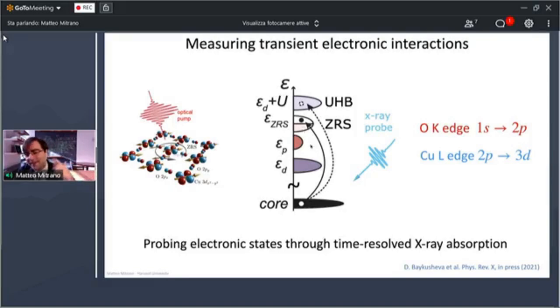The key thing that you have to keep in mind for the interpretation of what comes now is that by absorbing X-rays from core states, we can actually induce transitions into unoccupied states and therefore measure the unoccupied density of states of this material. We can send electrons into the Zhang-Rice singlet, into an unoccupied portion of the Zhang-Rice singlet, or into the upper Hubbard band. And we performed X-ray absorption spectroscopy at the oxygen K edge and the copper L edge.